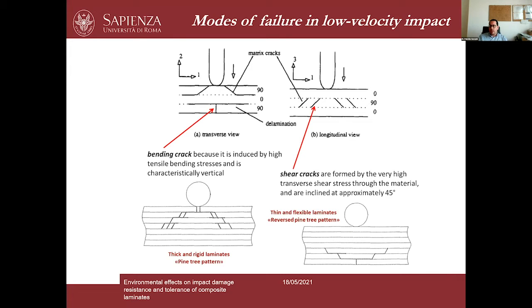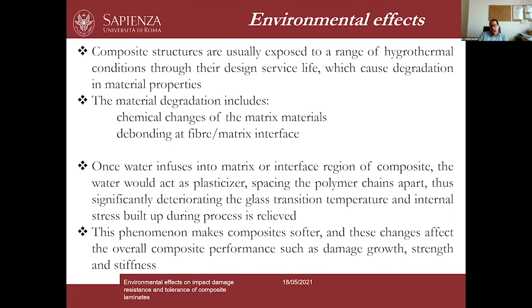So on the surface, you cannot see anything, but instead you have a significant damage inside. And so the post-impact residual strength of the composite laminate is usually significantly reduced. And in addition to the impact damage and to the vulnerability of composite materials, we have also to mention that these composite structures, during their service life, they are usually exposed to a wide range of hygrothermal conditions.